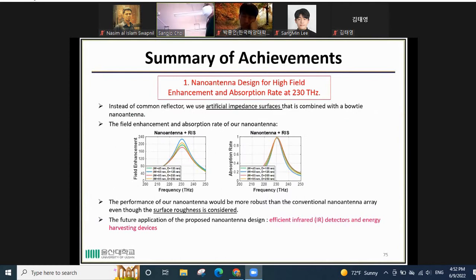So this is the summary of our achievement. For the first one, nano antenna design for high field enhancement and absorption rate at 230 terahertz. We use an artificial impedance surface instead of a common reflector, and this is the field enhancement and absorption rate of the antenna. It is showing 220 field enhancement with almost perfect absorption at 230 terahertz.